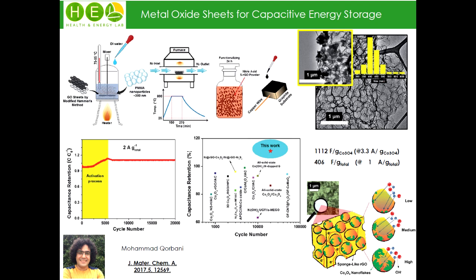When we put the electrode inside the electrolyte, at first it's not possible to benefit fully, but repeating the cycle number for a while, we can activate all of the active material. It's the reason for increasing the capacitance, for example, after 5,000 cycles.